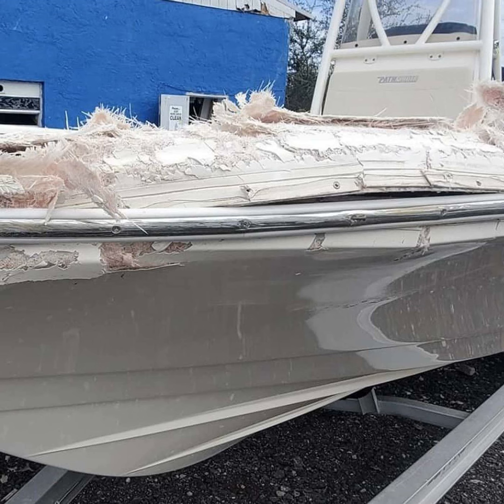So if you're punctured all the way through your laminate, you're going to do everything you can to get to the backside of it. If you can get to the backside of it, what I suggest is you do your first grinding on the backside, and let's just say, for example, that you have a 6 inch by 6 inch hole that's punched through the side of the boat mostly, and you can get to the backside of it, and you can prep an area that's 24 by 24 inches, or 18 by 18 inches would be good.